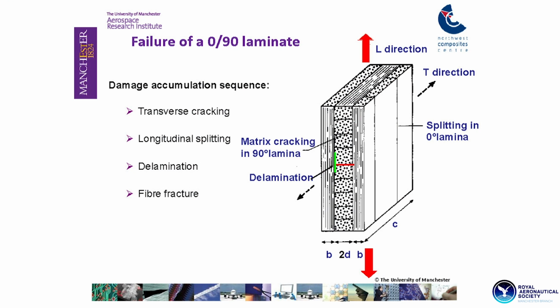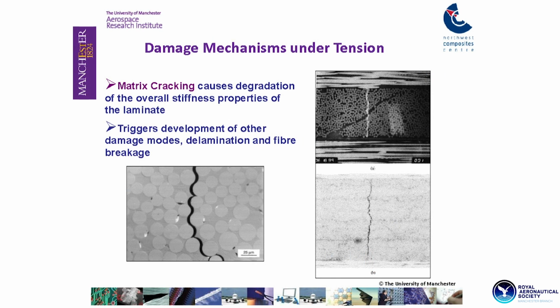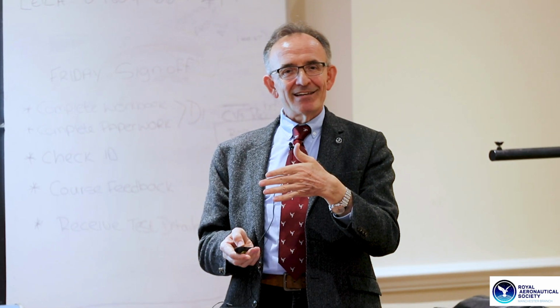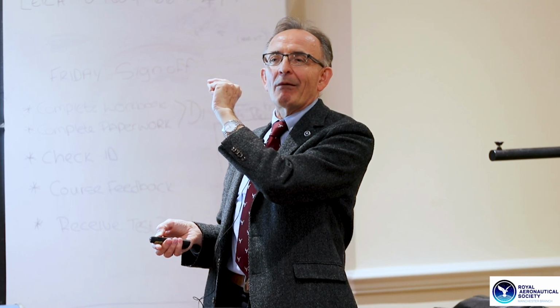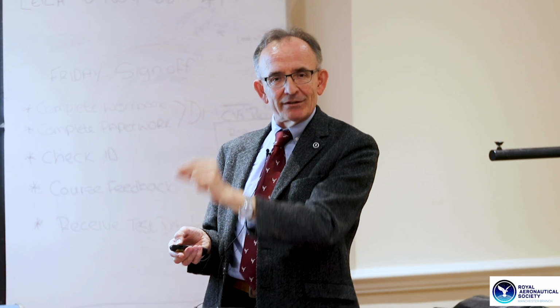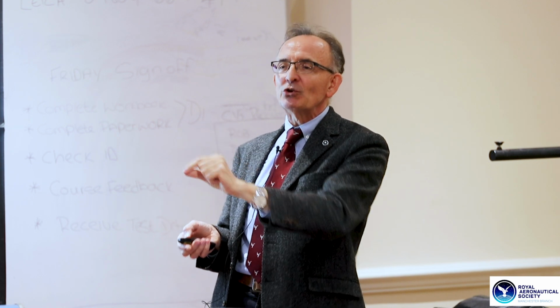And here we can see how damage develops in those laminated carbon fiber constructions. This is a very simple 0-90 layup, and if we load it, say, along the L direction in tension, we're going to see that cracks start to develop. These are the matrix cracks in the 90-degree ply. Those cracks, we focus on this one. At the tip of the crack now you have a three-dimensional stress field, very high stresses, but not high enough to break our zero fibers, but high enough to delaminate the zero layer from the 90 layer. So we have matrix cracks that trigger delaminations at the tip of the crack. Yes, they are matrix crack induced delaminations.